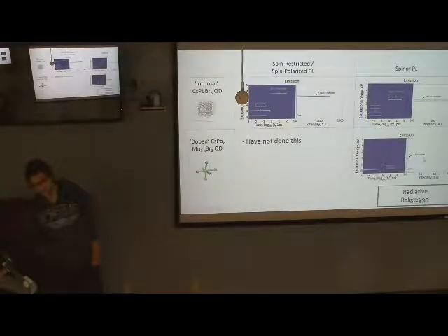But I remember from your poster, one of the main results was that you will have emission from the D state only if you include spin orbit. Yes, and this is with spin orbit. So it is small, but not zero. If you don't have spin orbit, then it's completely dark. Right. I was going to say, in experiment, they see that this peak here should be the same order of magnitude as this peak. But in experiments, they probably don't have a single manganese impurity.